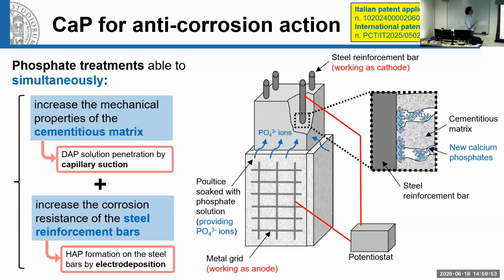By taking inspiration from this, we performed some studies and we recently filed a patent at the national level and then international level. The idea is, again, to treat like a concrete pillar with steel bars. You apply phosphate ions from the exterior, and by a single treatment, you are able to improve both the cohesion of the cementitious layer, so you make it denser, more cohesive, you improve mechanical properties, and you can improve the corrosion resistance of the steel bars. So by a single treatment, you can obtain this double effect.